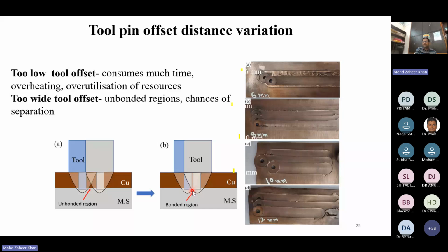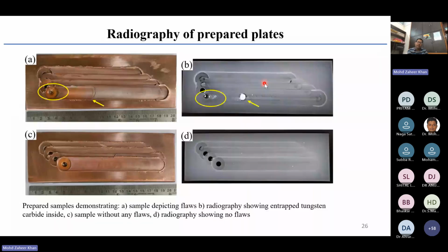So what we did is that we tried several experiments. That is, the tool offset was kept as 6 mm, 8 mm, 10 mm, and 12 mm. And we then performed X-ray radiography to serve two purposes. So after cladding these plates with different offset distances, the entire copper cladded plate was sent for X-ray radiography, and X-ray radiography revealed this result. You can see the photographs, and as you can see over here in this portion, the tungsten carbide tool has actually broken down because of some reason, some intermetallic formation or whatever has happened, and this is stuck up, and this is again a failure.